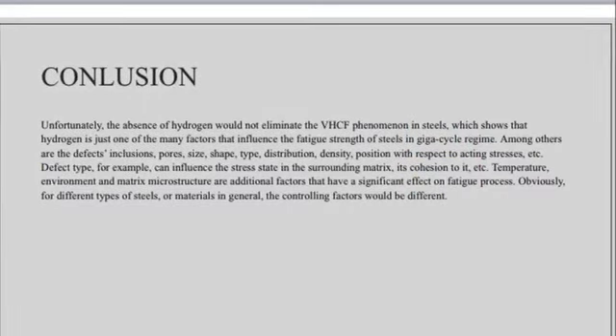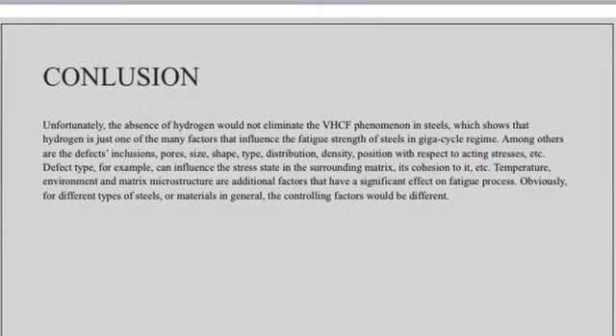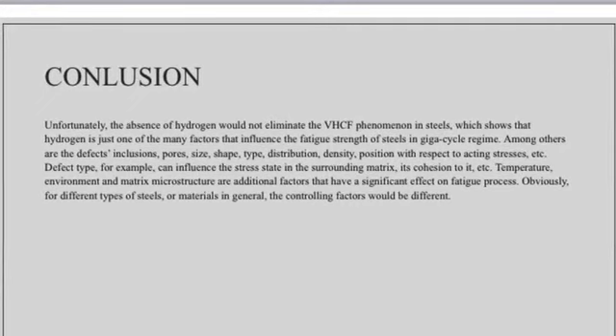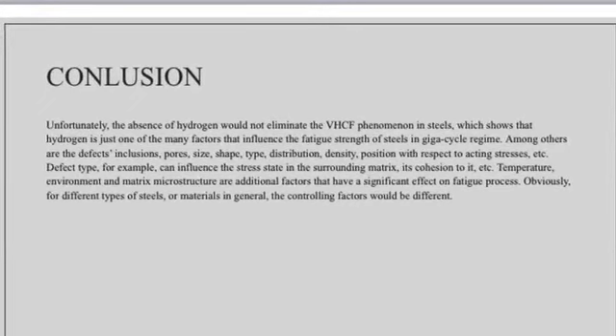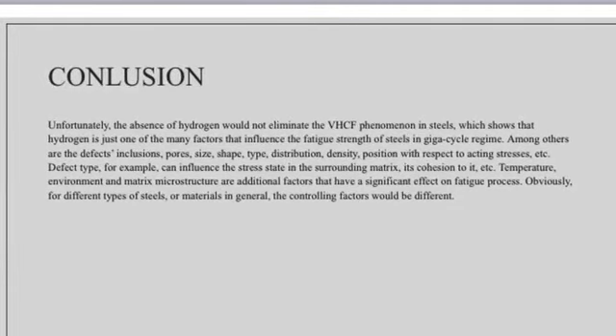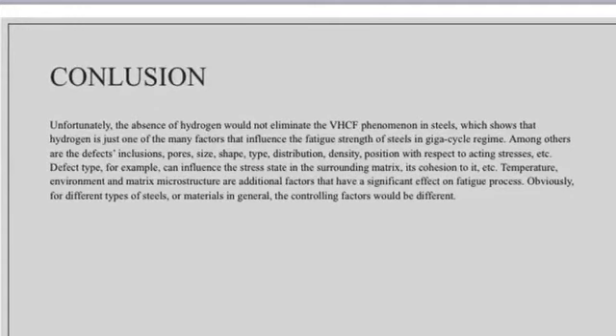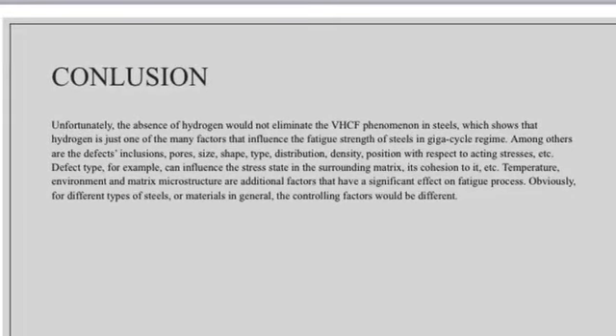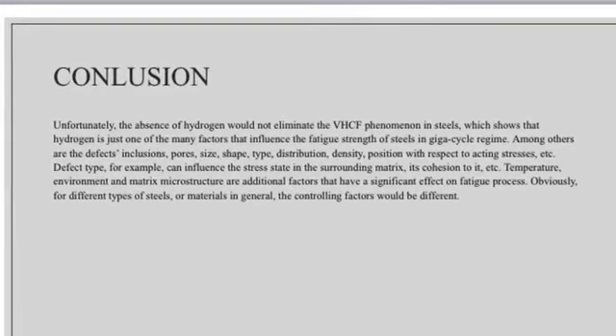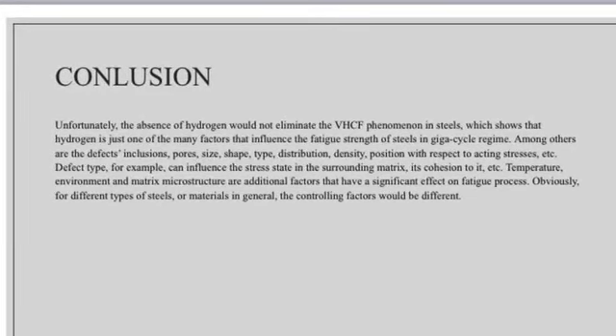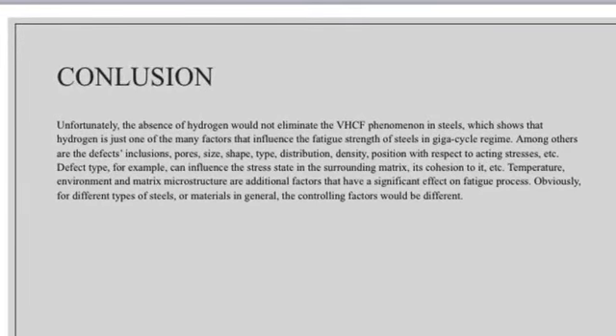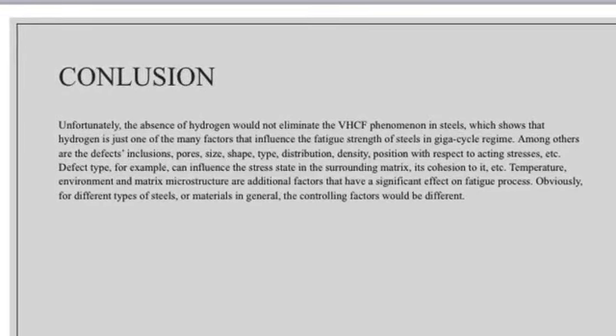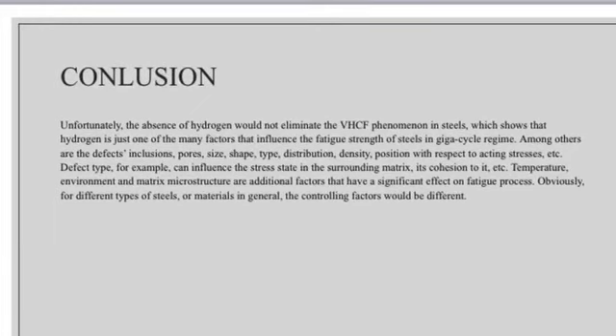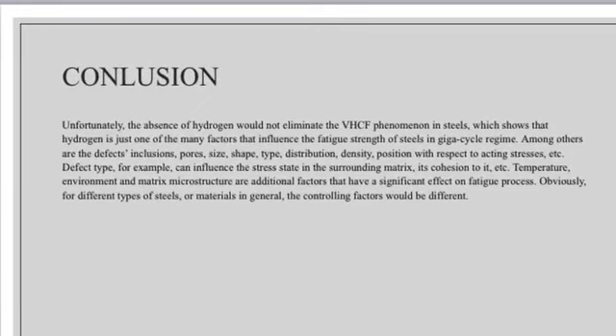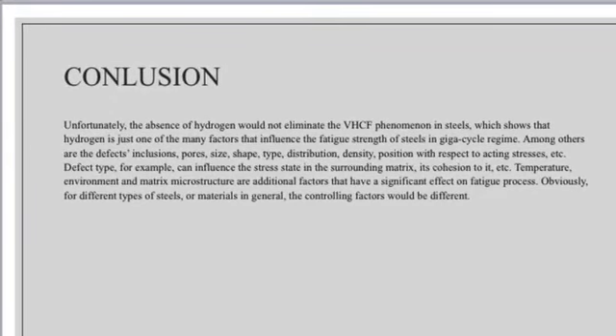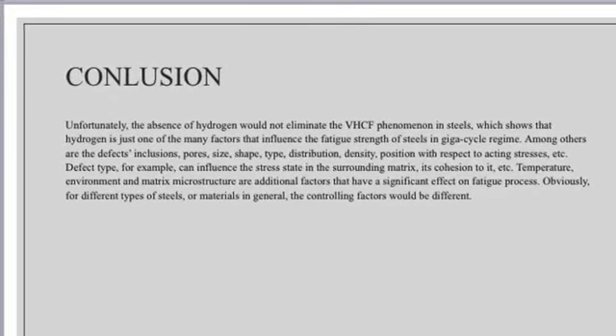Unfortunately, the absence of hydrogen would not eliminate the VHCF phenomenon in steels, which shows that hydrogen is just one of the many factors that influence the fatigue strength of steels in the gigacycle regime. Among others are the defects, inclusions, pores, size, shape, type, distribution, density, and position with respect to acting stresses. Defect type, for example, can influence the stress state in the surrounding matrix and its cohesion to it. Temperature, environment, and matrix microstructure are additional factors that have a significant effect on the fatigue process. Obviously, for different types of steel or materials in general, the control factors would be different.